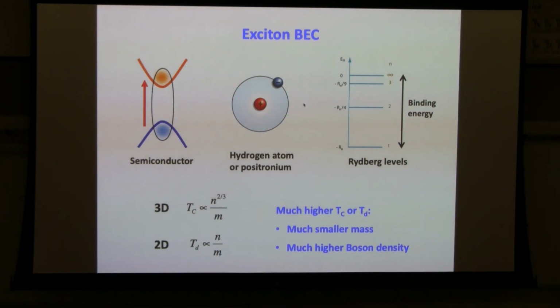Okay, so for excitons, the mass is a lot smaller compared to the atoms. It's about a factor of 1,000 smaller. So when you look at this formula here, the Tc in 3D and the degeneracy temperature for 2D, if you have 1,000 times smaller mass, then the temperature scale will go up by a factor of 1,000 or even more. And at the same time, you can also sustain a much higher exciton density compared to the atomic density scale, so that the numerator here, the N, you can also get to a much higher density compared to the atoms. And as a result, you may expect the condensation temperature in 3D to go up by many orders of magnitude compared to the atoms.